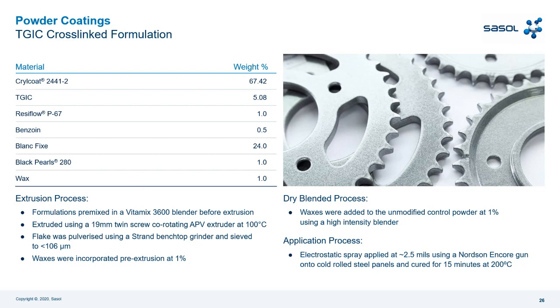So Sasol also with this technology uses 1% in pre-extrusion and in post-extrusion. The extrusion process is like before for the epoxy-polyester technology, for the HAA technology, and for the TGIC technology. The dry blend process is the same, and the application process with the gun is the same gun, and we put the oven at 15 minutes at 200 degrees, like before.